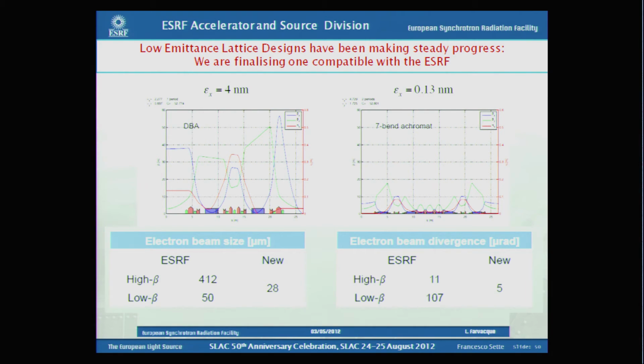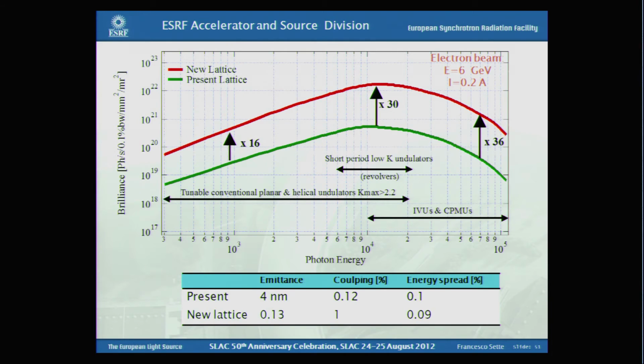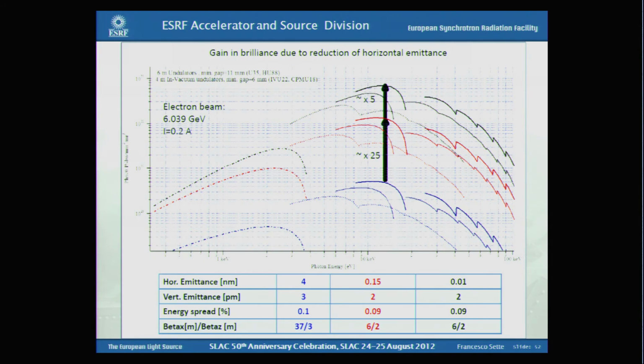And as you can see, the source size in the horizontal direction will go down to 28 microns, and the divergence to 5 microradians. If we look at the effect in terms of brightness, this is summarized here with optimized undulators. At low energy we will have an improvement of about a factor 16. In the X-ray region of about 10 kilovolts it is a factor of 30, and then in the harder region of something like 60 kilovolts a factor of 36. And this is obviously a very important improvement for all those nano imaging approaches that I was showing before, that will enable extremely new possibilities.